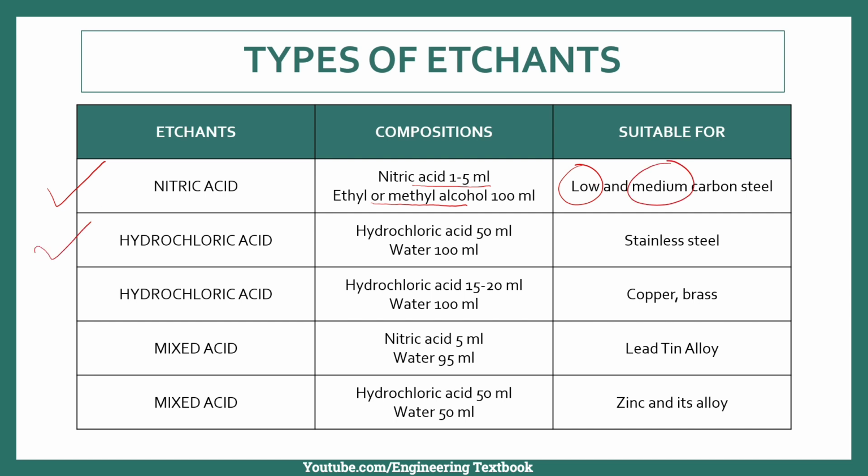Second is hydrochloric acid: a mixture of 50 ml hydrochloric acid and 100 ml water, suitable for stainless steel.